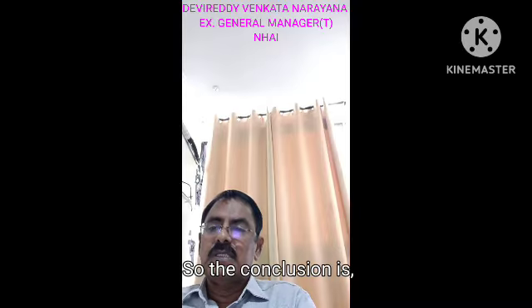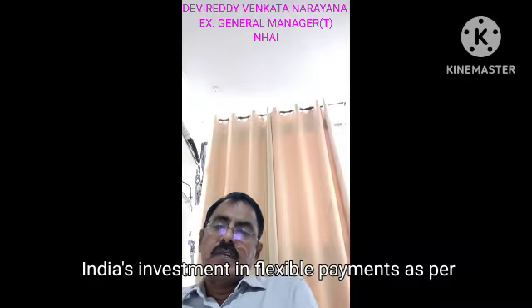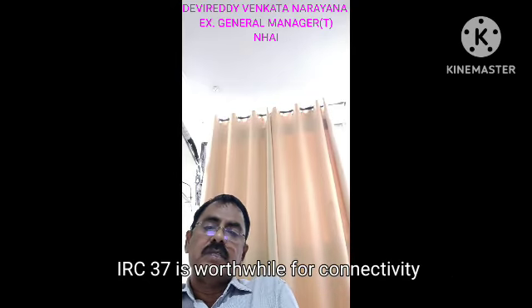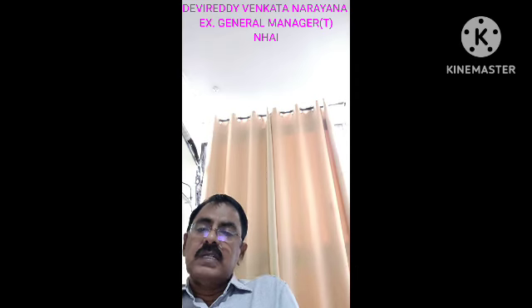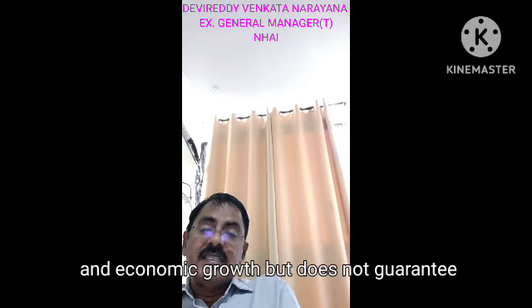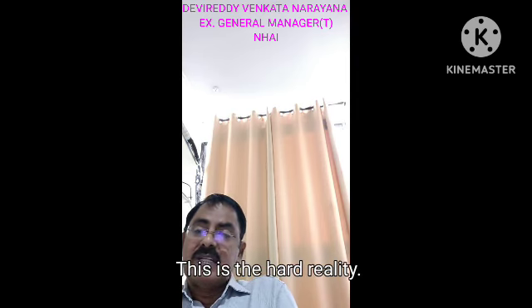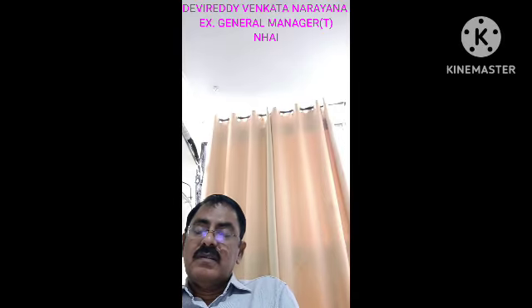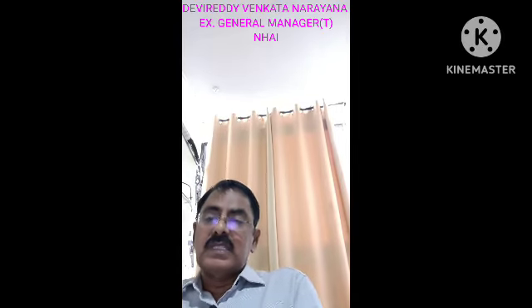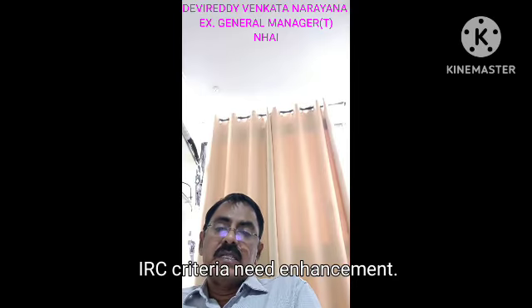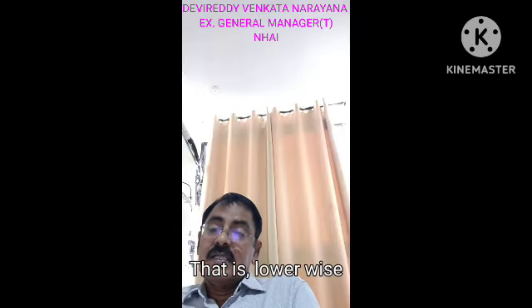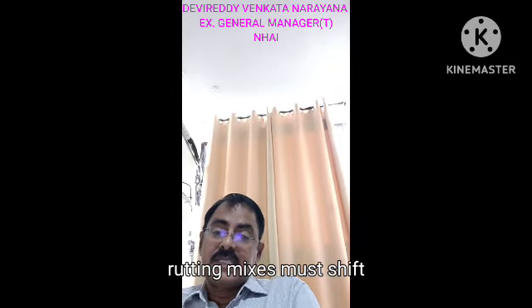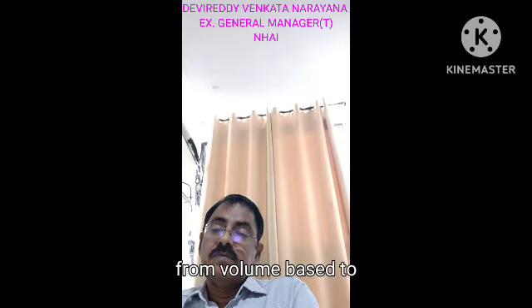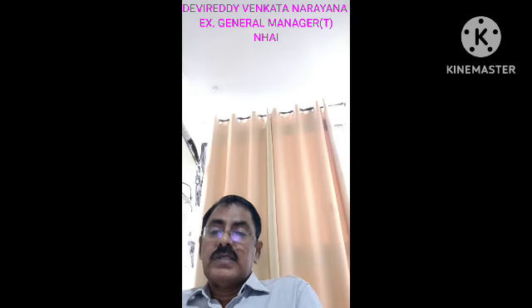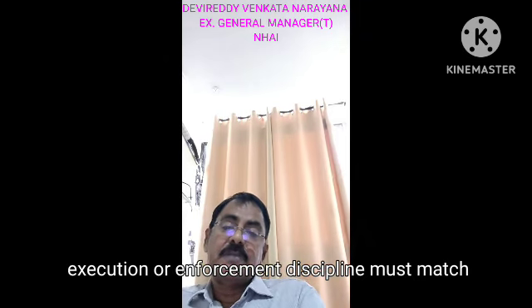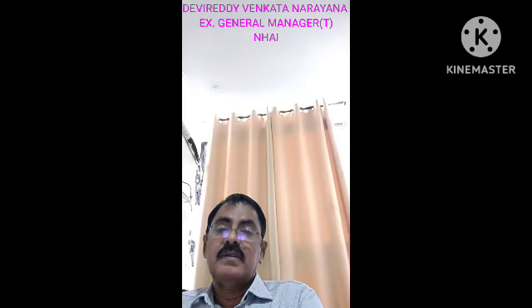So the conclusion is: India's investment in flexible pavements as per IRC 37 is worthwhile for connectivity and economic growth, but does not guarantee rutting-free surfaces. This is the hard reality. To ensure rutting resistance, IRC criteria need enhancement. That is layer-wise rutting. Mixes must shift from volume-based to performance-based, and execution or enforcement discipline must match design intent.